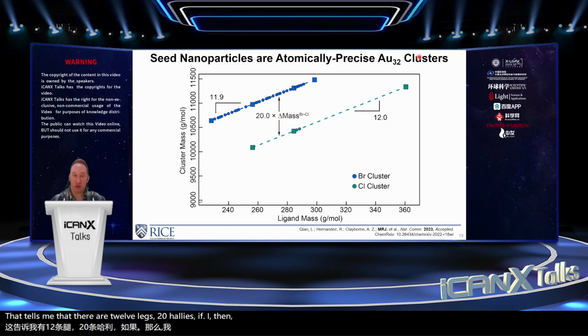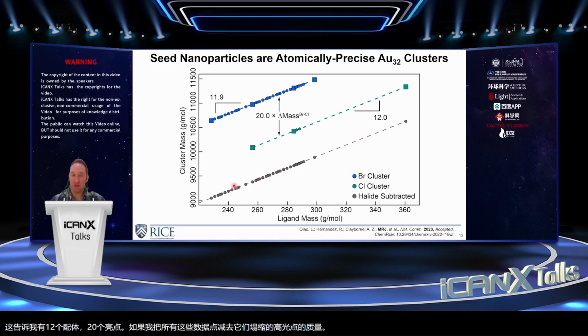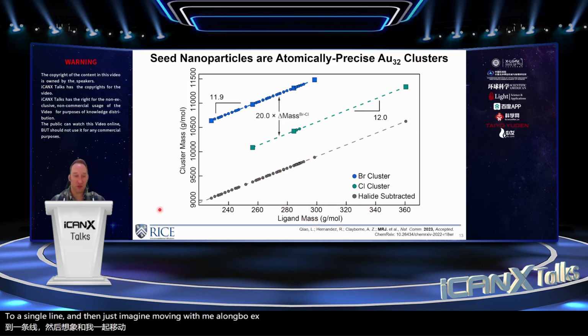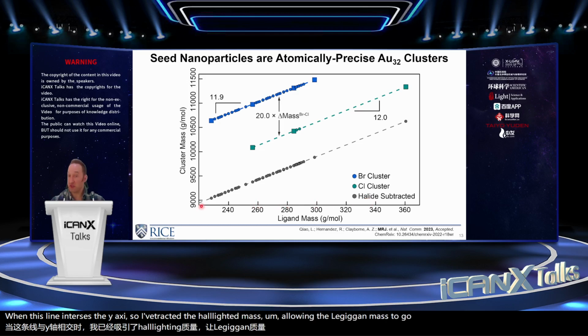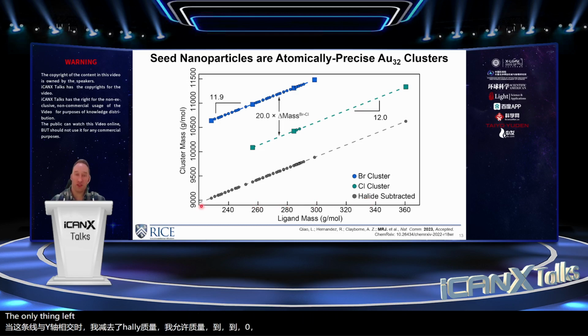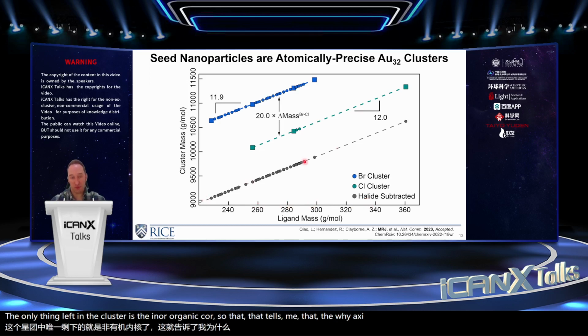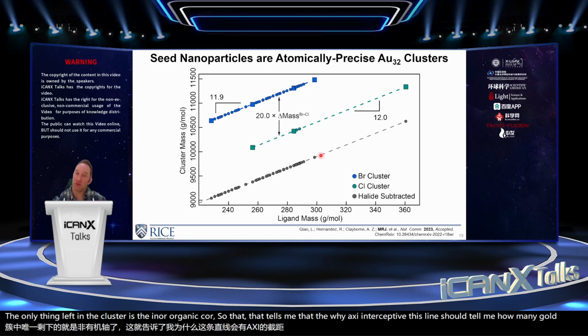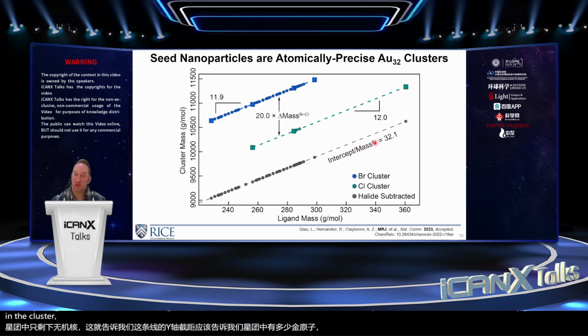If I then take all of these data points and subtract the mass of the halides so that they collapse onto a single line, and then just imagine moving with me along the x-axis all the way to the left to where this line intersects the y-axis. So I've subtracted the halide mass, I'm allowing the ligand mass to go to 0. The only thing left in the cluster is the inorganic core. So the y-axis intercept of this line should tell me how many gold atoms there are in the cluster. And if I divide the intercept by the mass of gold, I get 32.